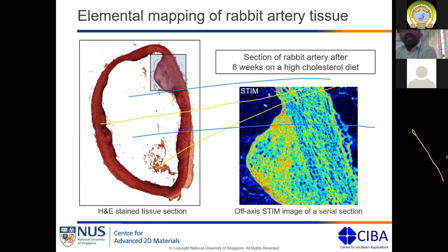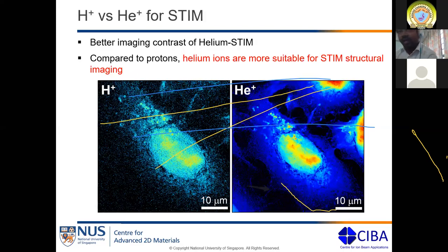The next is the comparison between hydrogen and helium ion beam for STIM imaging. For hydrogen, the STIM imaging is not very good, because there are a lot of grainy patches and it is noisy. The resolution is actually bad, and the contrast is also poor. If you go to helium ion beam imaging, you can see good contrast. You can resolve the finer details in the cell. You can resolve the nucleus better, and you can even go into the nucleus and see finer detail inside it. So in that sense, helium ion beam works much better than proton beams for this kind of STIM imaging mode.